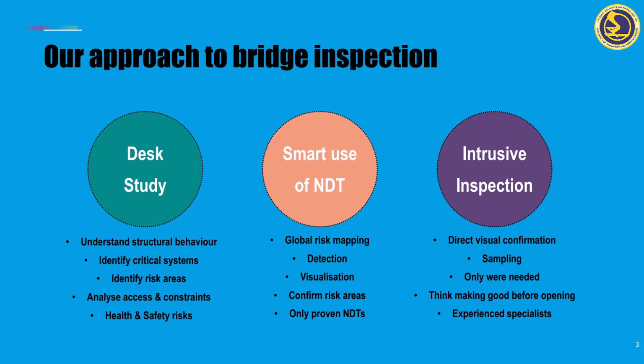We can then supplement that desk study with visual inspection on site, which typically tells us a lot about the condition of the structure. And then we can combine this with non-destructive testing technologies. We need to make smart use of these systems. We need to use them to establish a global risk mapping of the structure, to detect certain pathologies and damages, to visualize them, and to confirm, therefore, which are the critical areas for intervention.